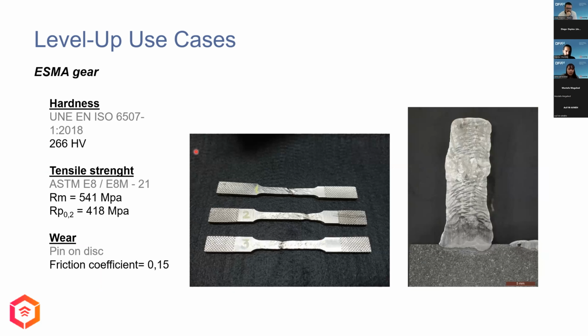Those are the results of the mechanical properties tested in IMEN laboratories during the process parameter obtention. We tested microhardness on a part manufactured with wire, also tensile strength following the ASTM E8 with subsize samples. And also we tested the wear using a pin on disc test.